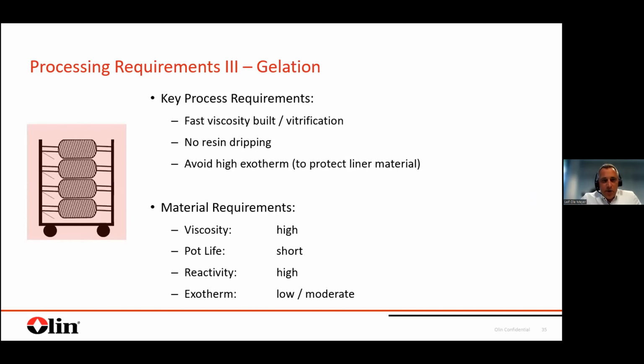So during gelation, the material is transitioning from the liquid state into the solid state, or first into the gel state. And this is what we call the so-called vitrification of the material. So the material gets hard but not yet fully cured, and viscosity moves from high over gelation basically to infinite. The key requirement in this process is still to avoid high exotherm. This is where a lot of the chemical reaction of the cross-linking of the epoxy takes place. So this is really one of the critical steps where you need to make sure to protect your liner material.